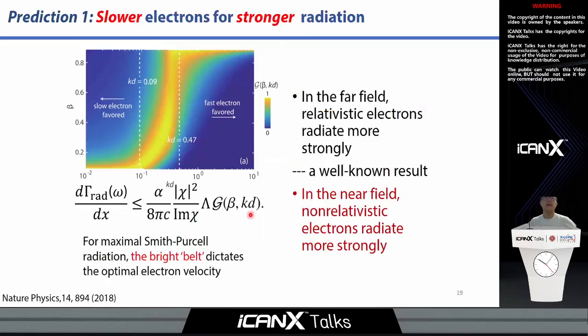So the first one is a regime where slow electrons can radiate more strongly than fast electrons. We obtain a specific upper limit for the Smith-Purcell radiation, highlighted by this G function, which has two arguments: the electron velocity normalized by the speed of light, beta, as well as this dimensionless impact parameter kd, indicating the separation of electrons compared to wavelengths. So we see this G function looks like this, okay? It's highlighted by this bright belt.